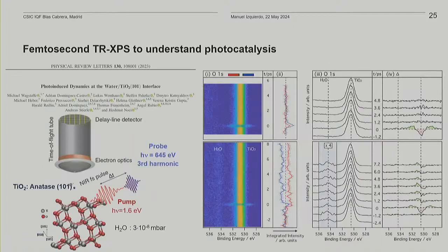The second example I'm going to present is an example on photocatalysis, and in particular water splitting on titania. So this is kind of like a seminal example. Basically, it's known that photocatalysis of water occurs only on the anatase phase of titania due to the bond distances at the surface. And what the colleagues did, again, was a pump-probe experiment because it's a photocatalytic process. So they again excited with something around 800 nanometers, and they probed with 645 electron volts because they wanted to see the dynamics at the oxygen 1s.